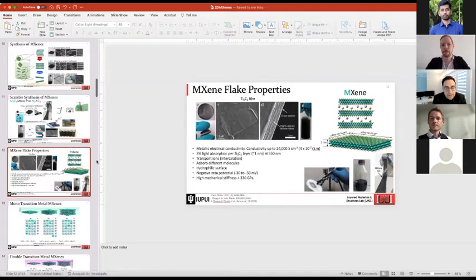So the best way to think about MXenes is from the bulk perspective. And that's really my favorite approach, basically looking at the literature to identify what the bulk properties are first and see whether it follows that or whether it has effects of 2D. Now, carbides are generally known to be conductive ceramics. And that's something that has been extensively researched in the 1980s and earlier. The carbides were called basically conductive ceramics, which is unique compared to the oxide ceramics that everyone is familiar with. And that's basically from the nature of the titanium and carbon bonds that creates this unique structure that is electrically conductive.